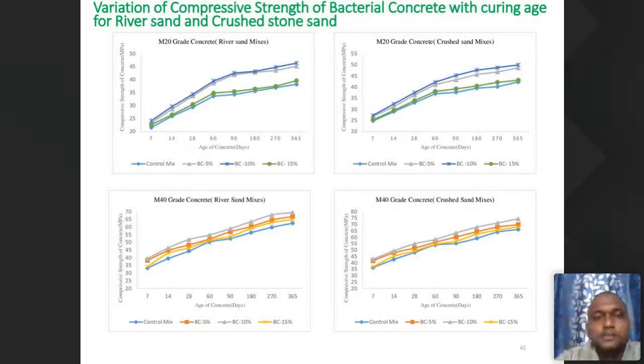If you observe these diagrams, the first one is M20 grade concrete with river sand. The second one is M20 grade concrete with crushed sand mixes. Likewise, here are M40 grade concrete with river sand and with crushed rock sand. There is an increase at every level. In the first graph, M20 grade concrete, I took specimens at 7, 14, 28, 60, 90, 180, 270 and 365 days, casting cubes likewise. We did the experimental work at different stages from 7 days to 365 days, and there is an increase at every level.